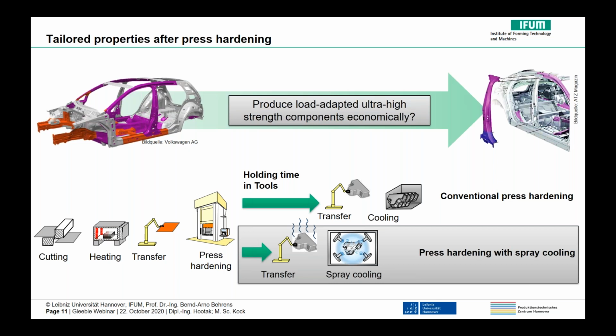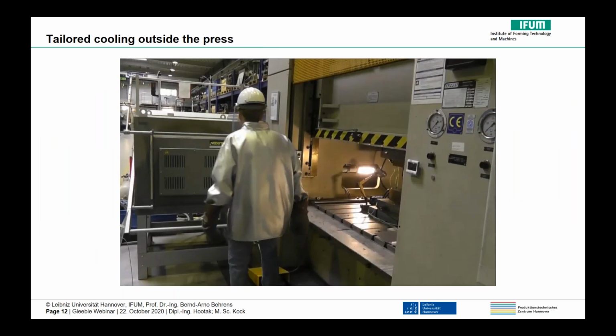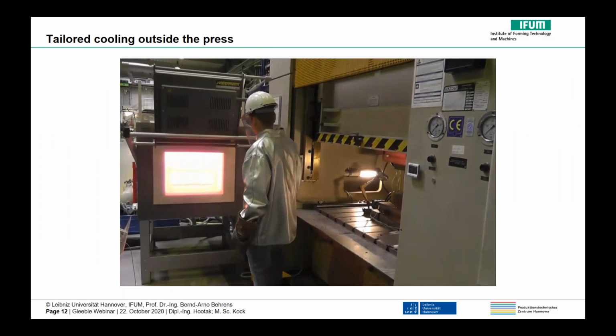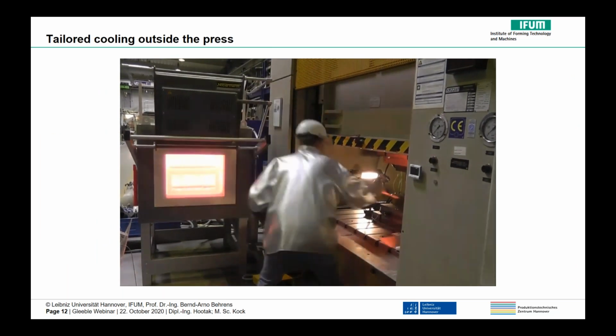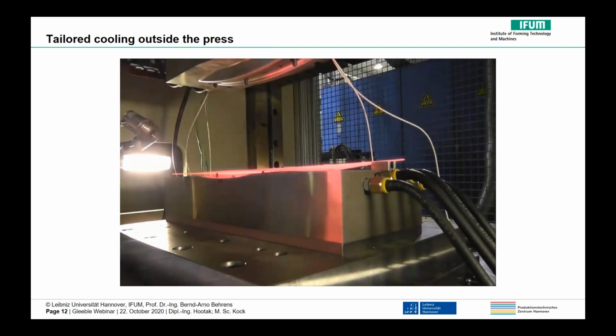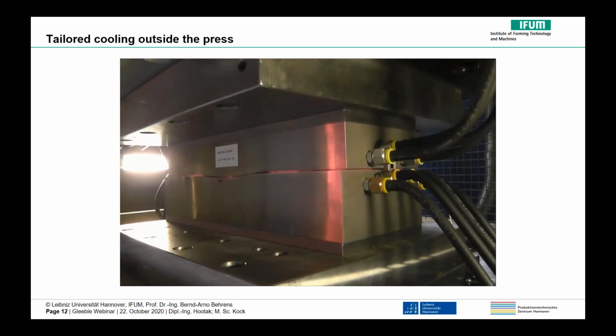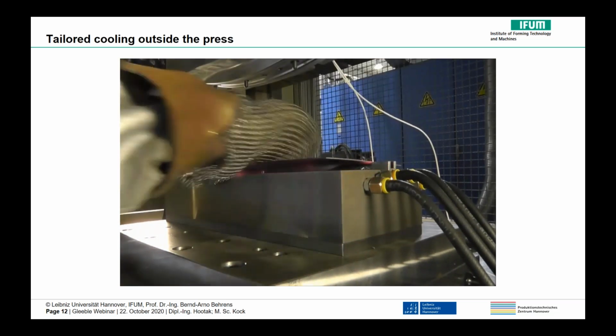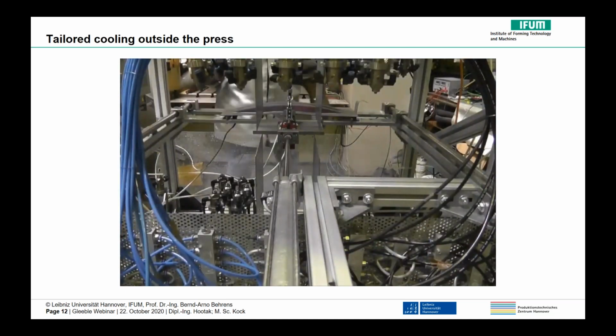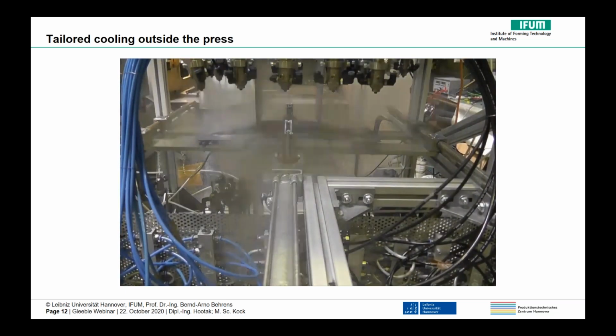The solution is a special spray field cooling, in which water and air spray is applied to the component areas to be hardened, while other areas are cooled slower. In our video, you can see an example process where a demonstrator component is treated in this way. After the sheet metal has been heated up in an oven, it is inserted into the tool, formed, and then transferred to the spray cooling. Subsequently, the partially adapted cooling takes place.